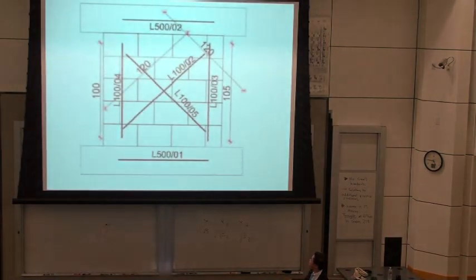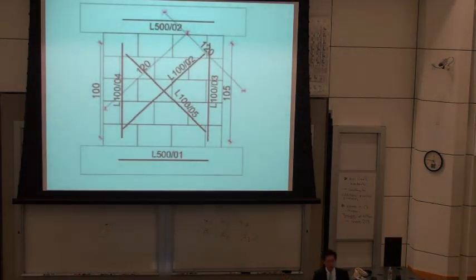Here is the test in reality. So you apply your vertical force, then apply your cyclic shearings, three steps at the same displacement. With the same displacement, then you go up to the next higher displacement step. Here are just some pictures from the instrumentation. In this case, we used just simple LVDTs. And probably this is also a reason why the tests are mostly stopped at 80% of the maximal shear force or horizontal force. It's because we want to save the instruments.